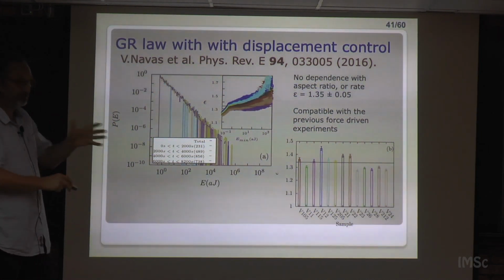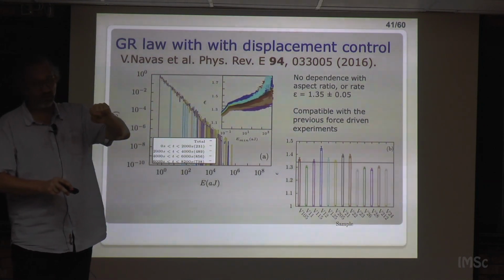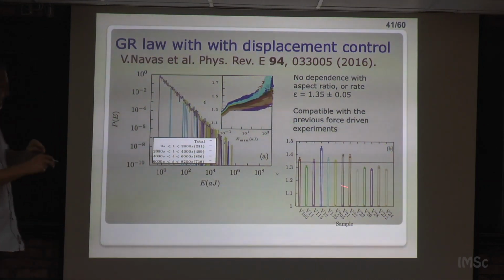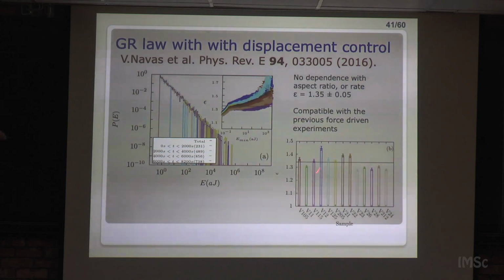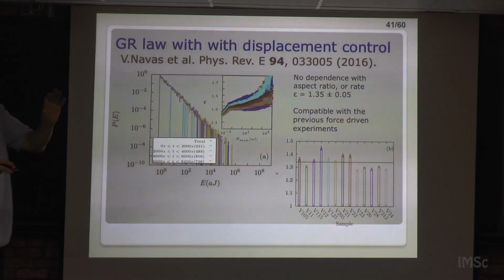It's just you have aspect ratios which are 1 to 6 and others which are 6 to 1. And the exponent is rather the same. The variations you have are more like sample-to-sample fluctuations. So everything is around 1.3 something, 3.5. The other one was 3.9.